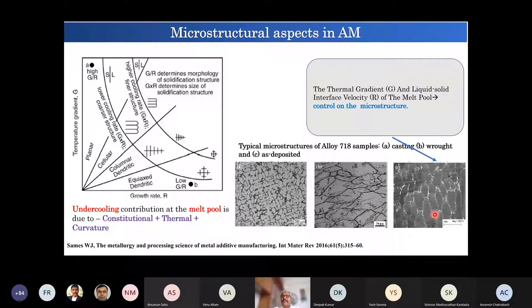because of the precipitates or the second phases, which are generally very difficult to generate in these cases. They inevitably occur because in this case we do not do anything that suppresses the formation of these phases. It's some kind of non-equilibrium cooling. So if those thermal conditions are suitable for generation and growth of these precipitates, then one can get them. Sometimes they are undesirable. In that case, post-deposition heat treatments are applied, and these precipitates are made to dissolve in the matrix and the segregation has to be minimized.